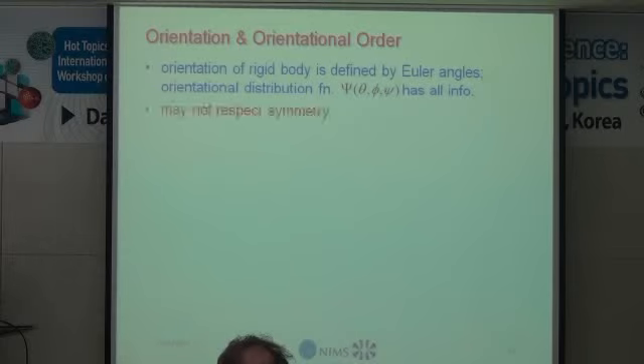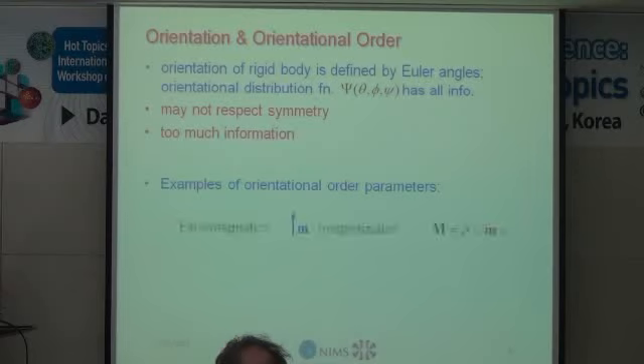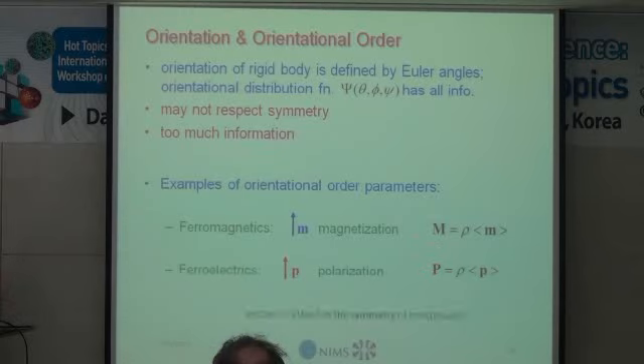But it may be that the distribution doesn't explicitly respect the symmetry of the particles. And there may simply be too much information. Maybe it's not necessary to have all that information to have an adequate description of the behavior of the materials. So a couple of examples may be useful to look at. In magnetic materials, there's a magnetic moment per unit cell, and the order parameter is the magnetization, the magnetic dipole moment per volume. And in ferroelectrics, it's the same. There's electric polarization, and the order parameter is the electric dipole moment per volume. And so these are useful quantities, and they kind of give a hint as to how to proceed in liquid crystals. And these are vectors related to the symmetry of the constituents of the material.